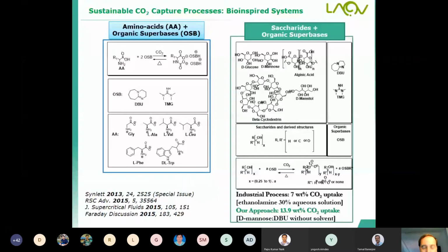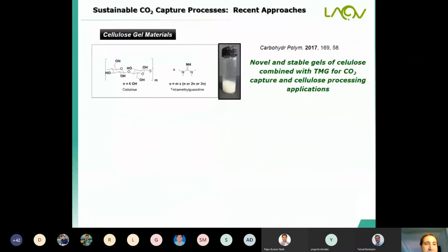But looking at these results, we tried to check cellulose, because cellulose is abundant, is natural, and it's interesting to combine in this kind of approach. And we tried to combine cellulose and tetramethylguanidine. In the presence of CO2, we observe the formation of a novel and stable gel of cellulose, and this is interesting for CO2 capture, but also for cellulose processing applications.